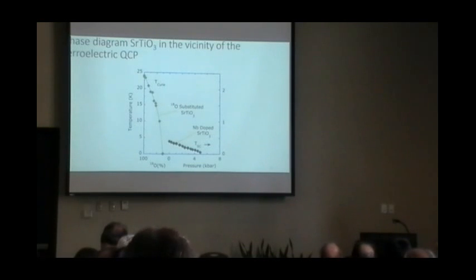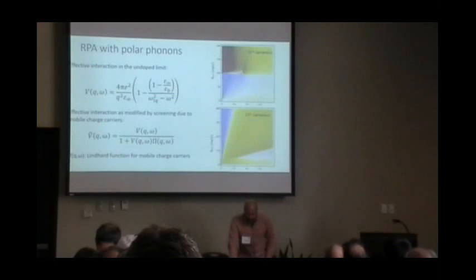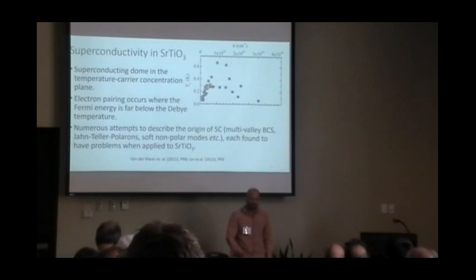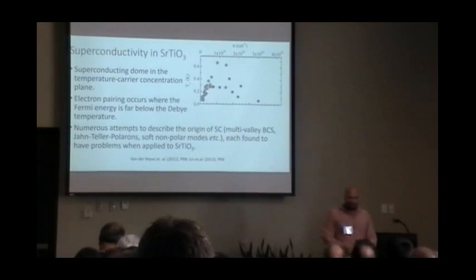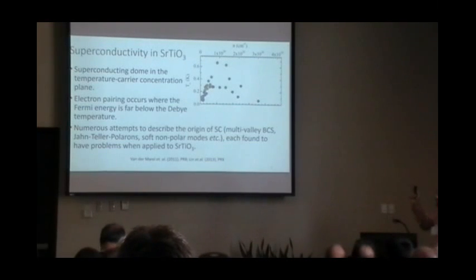Do you have a simple interpretation on why you have two different TC curves of the different substitutions? Let me go back to the slide. You are talking about this superconducting zone. There is a very strong variation in the literature on the TC. I said that it peaks at 400 millikelvin in this one slide, but there are some papers where it peaks close to 1 Kelvin, so it's really varying. I'm not aware of any change in that.